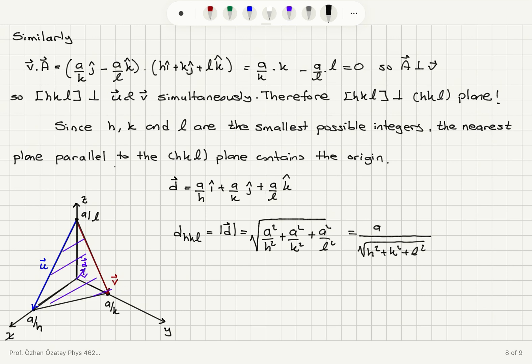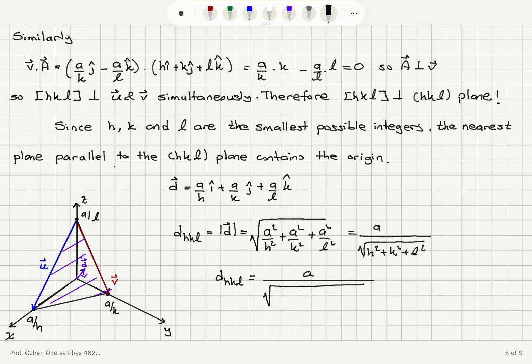This is true for a cubic crystal. In the lecture, we showed this by using the cosine theorem: we drew a perpendicular from the origin to the plane and looked at the angles this vector makes with the x-, y-, and z-axes. We wrote cos²α + cos²β + cos²γ = 1, which is the cosine theorem. That gives the same result. So the interplanar spacing between two parallel HKL planes is d_HKL = A / √(H² + K² + L²).